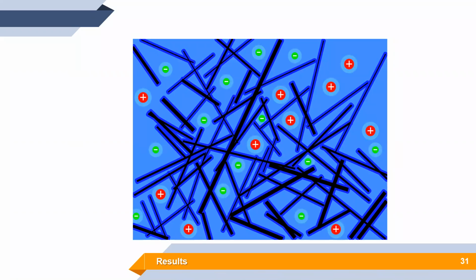we see that we can find solvent molecules, water or others, in at least three different states. First, there will be solvent molecules in the volumes of the pores, which behave like a bulk solvent. Then we have the solvent molecules around the ions, creating the solvation shell, and those molecules will mimic the behavior of the ions. And then we have the solvent molecules at the surface of the gel matrix. So at least three states.